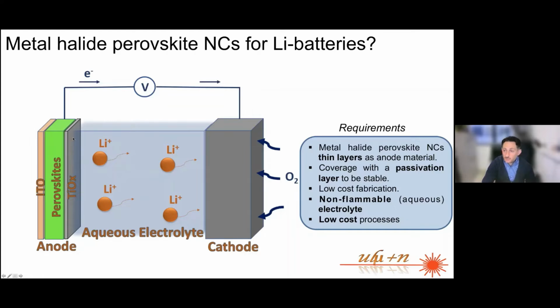A requirement here is that, in order to protect the perovskites, which are very sensitive especially to aqueous electrolytes, we need a passivation layer that will protect the perovskite structure from the water attack of the aqueous electrolyte. And then the cell is completed with a cathode. Of course, the requirements for this kind of energy storage cell are a low-cost fabrication, in order to be viable for potential applications, and a non-flammable, aqueous electrolyte. Apart from low-cost fabrication, the whole process, from the synthesis of the materials to the synthesis of the passivation layer, should be low-cost and scalable.